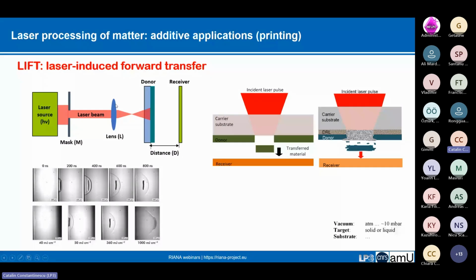The beam is shaped through a lens or a system, and it can also be positioned with another type of system. In this case, we use a mask, and the image of this mask is set at the interface of the donor, such that we can detach and transfer onto a receiver substrate, which is in close proximity of the donor, usually a few tens of microns all the way to a few hundred microns, depending on the needs. We can use simple or complex thin films. We can use direct irradiation, or a dynamic release layer, which decomposes and propels what we call the flyer or pixel.